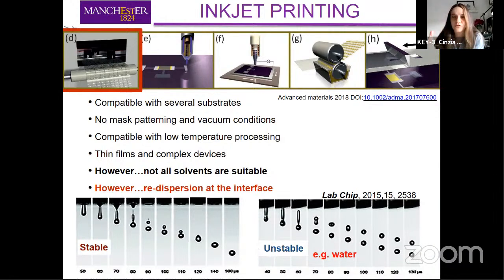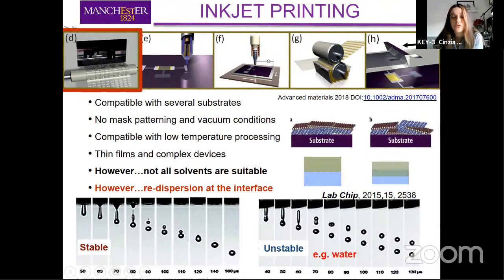And of course, the key goal when we use inkjet printing is to achieve full control on how the material is deposited on the surface. Otherwise, we can use drop casting. And so certain inks are not suitable. For example, water is well known to be a very bad solvent for inkjet printing. The surface tension is too high, the viscosity is too low. And so a water-based solvent will produce an unstable droplet formation, which is not suitable for device fabrication.